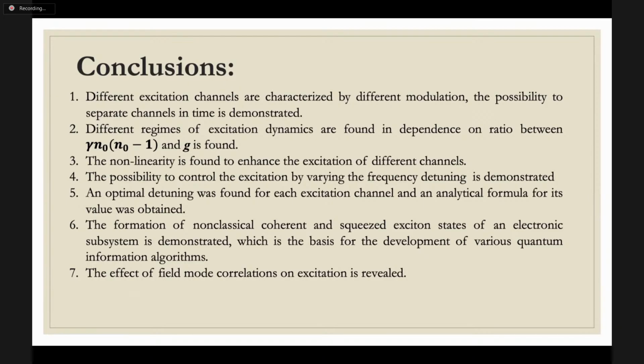One more interesting result is that the possibility to control the excitation by varying the frequency detuning is demonstrated. Then an optimal detuning was found for each excitation channel, and an analytical formula for its value was obtained. Then the formation of non-classical coherent or squeezed exciton states of an electronic subsystem is demonstrated, which is the basis for the development of various quantum information algorithms. And then the effect of field mode correlation on excitation is revealed.